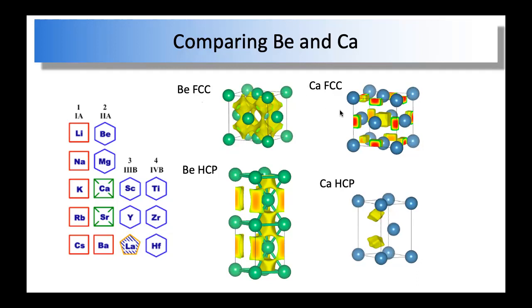For comparison, calcium is a totally different story. For 0 GPa calcium, if you calculate the FCC structure, then it is localized mostly at the octahedral sites, and for the HCP structure it also occupies the octahedral sites. For beryllium, the electron localization happens mostly at the tetrahedral site, for both the FCC and HCP structures. But of course, in the HCP structure, the tetrahedral quasi-atoms form pairs. So if you calculate the electron localization, they form a very strong chemical bond, and therefore stabilize the HCP structure and also reduce the c/a ratio because of this strong chemical bond.